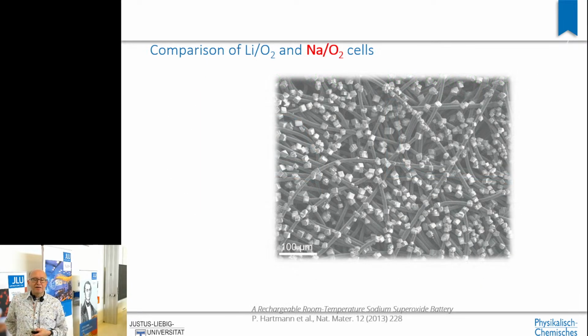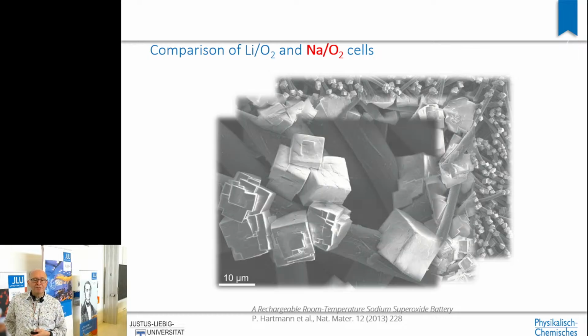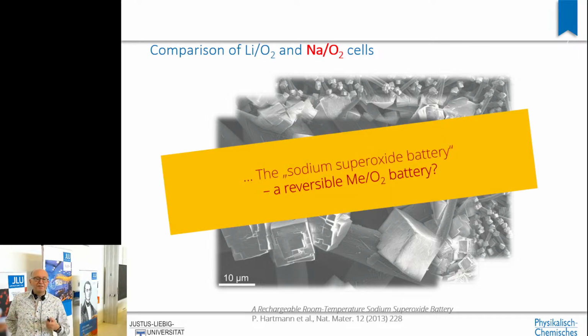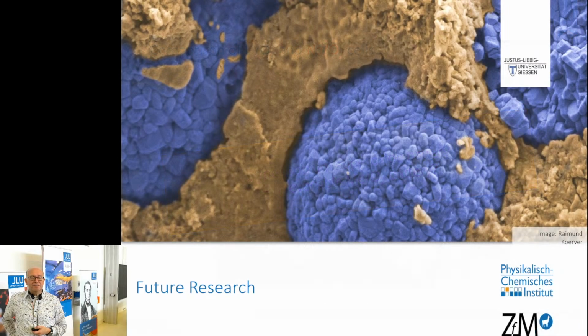And then you can take a carbon electrode and you nicely form during discharge these nice little cubes. Looks a bit like rock salt cubes, but this is pure sodium superoxide, which has the structure of pyrites or iron sulfides. And this is something that could be the path to a reversible metal oxygen battery. We still work on that. There's worldwide activity still in academia to overcome these issues, but for sure we need to spend quite some time to at the end come to real solutions for that.